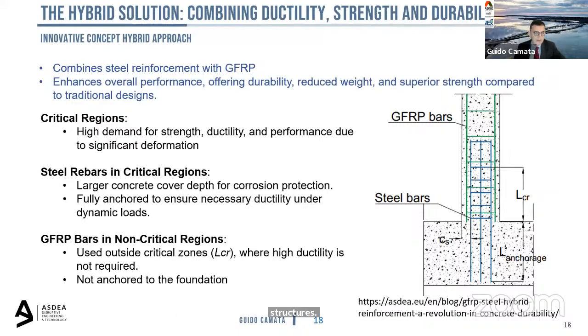Another idea is a new hybrid concept where combines the steel reinforcement with GFRP. And this was studied for seismic region. I'm a seismic engineer, so I was also concerned about the ductility. And the idea is to use an internal cage of steel rebars. The steel rebars are perfectly connected, anchored to the foundation. So also you can think about a joint, or think about a bridge pier, where you have the internal cage, and you can guarantee 10, 12 centimeters of reinforcement concrete cover. And all the critical region is designed with the steel reinforcement and also the confinement. So we can ensure large ductility of the performance because it's only controlled by the steel structure.